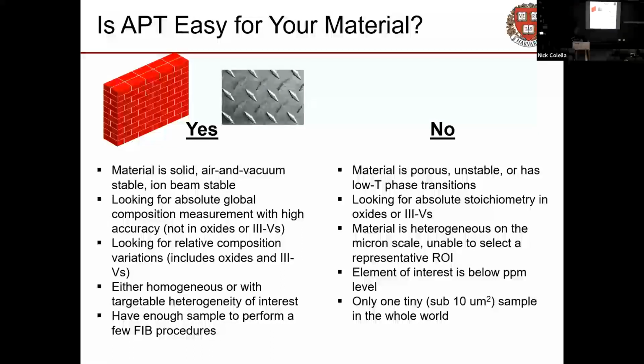Materials that don't work. Porous materials. There are a few materials with pores you can make work, but I don't recommend setting out to do that. Materials that don't like getting cold. If you've got a material that changes shape drastically as it cools down, then that pointy little needle we made at room temperature is not going to be a pointy little needle anymore by the time it hits 20 Kelvin. It's going to be some wonky shape. Absolute stoichiometry of oxides and III-Vs, not so great.